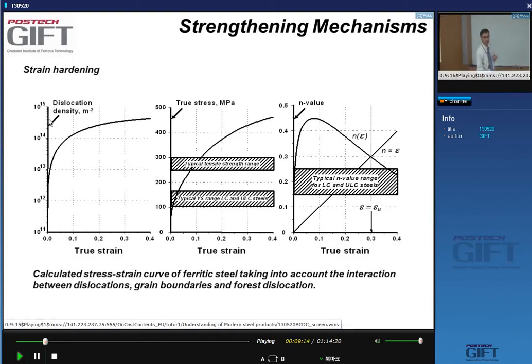It may seem like a strange unit, per square meter, but if you realize that a dislocation is a length, it means the dislocation density is expressed as a length of dislocation per volume. So if I have a unit volume, like here, for instance 1 meter by 1 meter by 1 meter, and I have a dislocation that goes right through this cube, then the dislocation density is 1 meter of dislocation in 1 cubic meter of volume. So the dislocation density is in meters minus 2. So it's a little bit of an odd quantity.